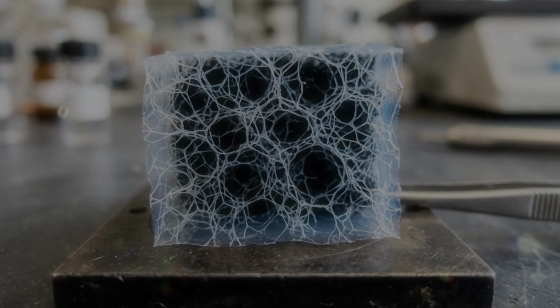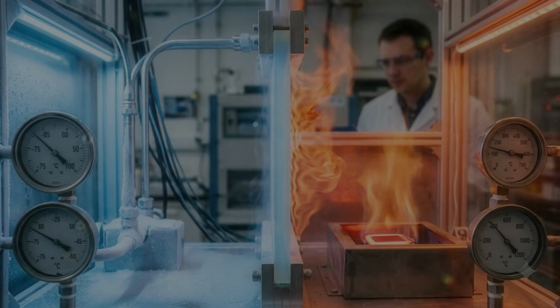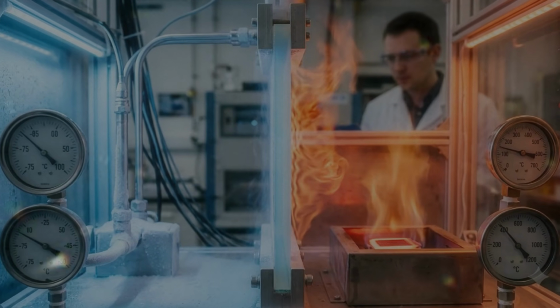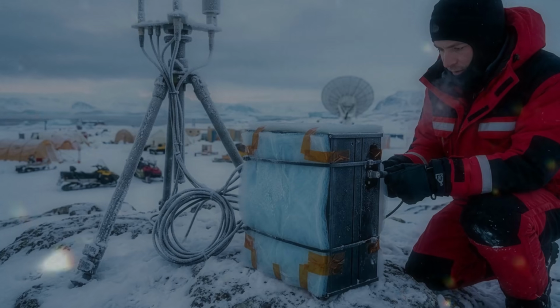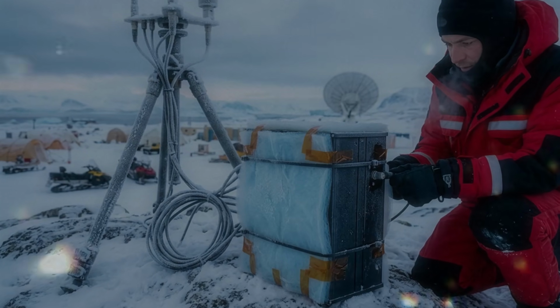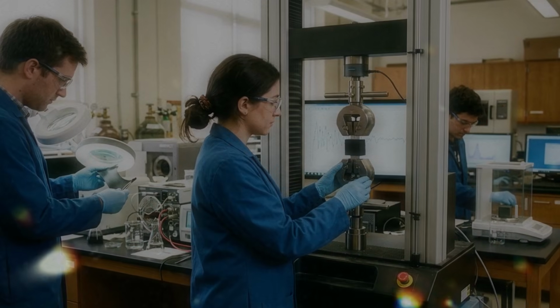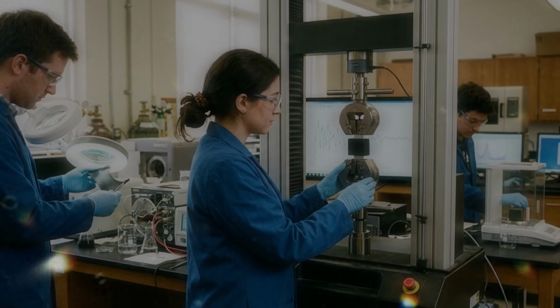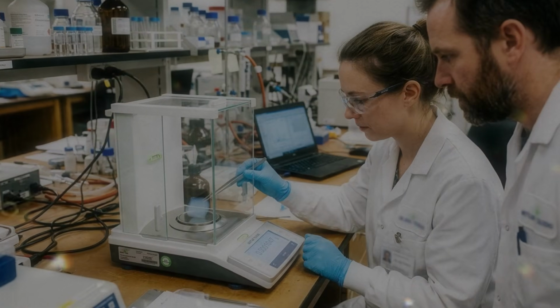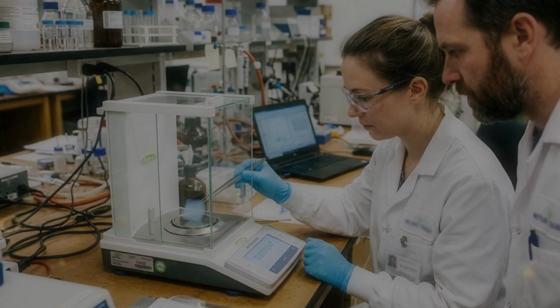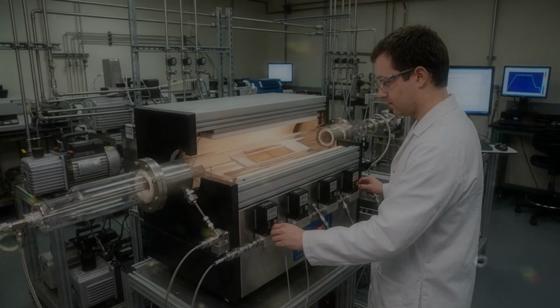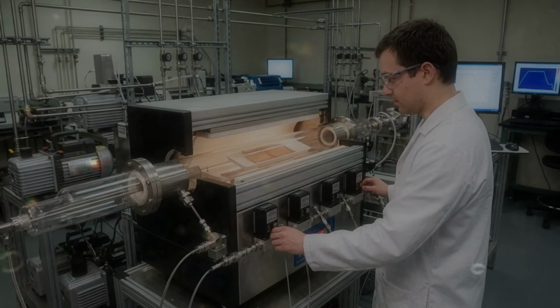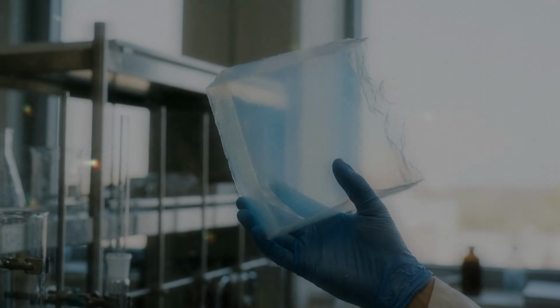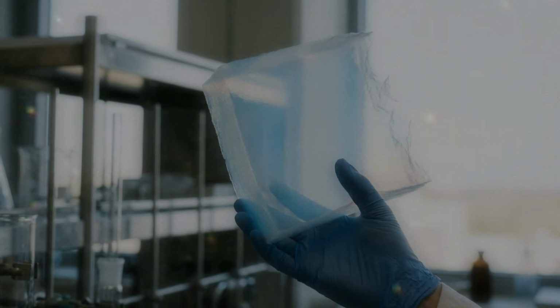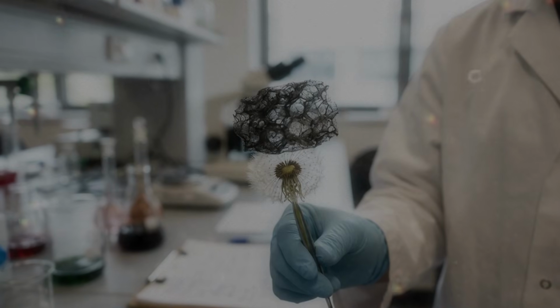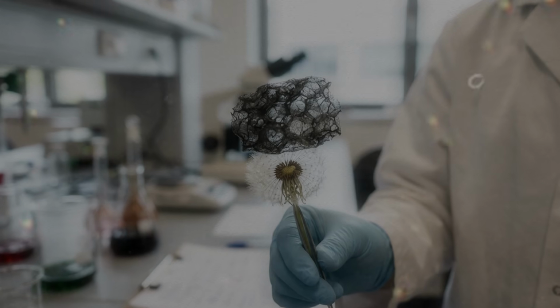The liquid inside the pores may also need to be exchanged for a different solvent. The original mixture can contain water, alcohol, unreacted chemicals, and products left behind by the gel-forming reactions. Some of these substances are unsuitable for the chosen drying method. The gel is therefore placed in a fresh liquid, allowing the unwanted contents of the pores to diffuse outward, while the new solvent moves inward. This exchange may be repeated several times. Each round removes more of the original liquid. Nothing dramatic appears to happen from the outside. The gel sits quietly in a container, looking as though it has achieved very little. Inside, however, molecules are slowly trading places throughout an enormous network of narrow passages.